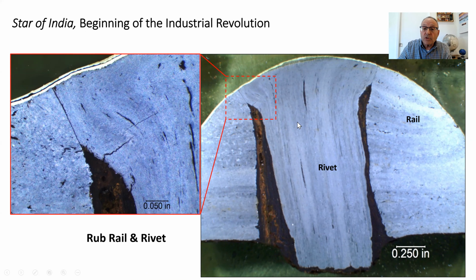And as you can see, it is a forged material. Here's the rivet. Here's the rail, and the rail is going out in that direction. And you can see how it was forged. And here, where you can see where it was swaged, the rivet was swaged in to hold the rail to the side of the ship. And so when we look at this, we see what look like stringers here. And these are non-metallic inclusions, or as we refer to it in the steel industry today, dirty steel. But these are non-metallic inclusions in the material.